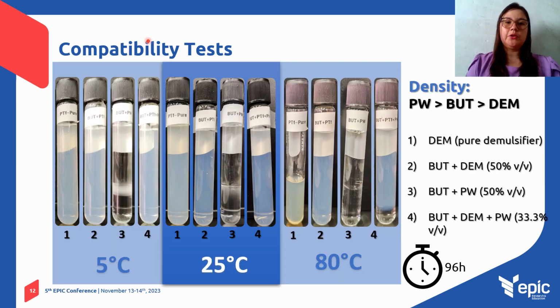The compatibility tests between the fluids that might be present in chemical injection lines were conducted at three different temperatures. One close to the seabed temperature, at 5 degrees Celsius. Another at 25 degrees Celsius, representing approximately the temperature where the chemicals are stored at the platform, and the last one at 80 degrees Celsius, representing the temperature almost at injection conditions. All the fluids were manually homogenized for 2 minutes and then visually monitored for 4 days at 24-hour intervals, considering a low flow rate of injection.